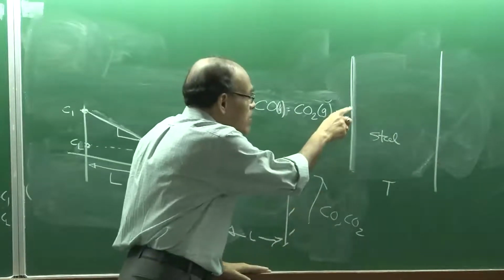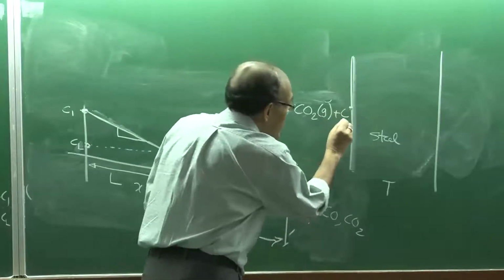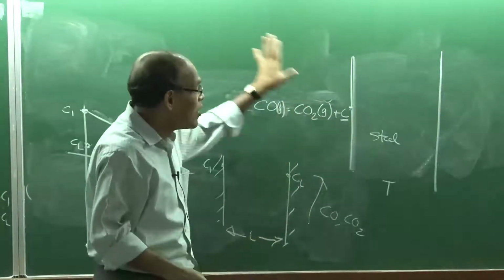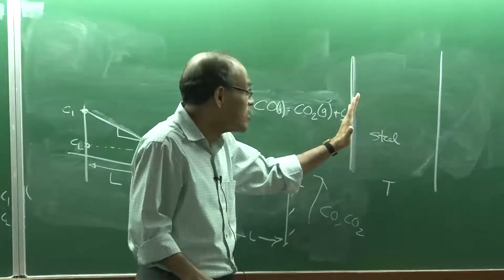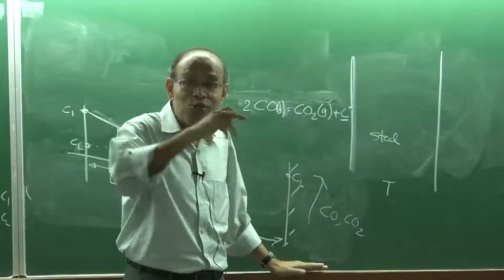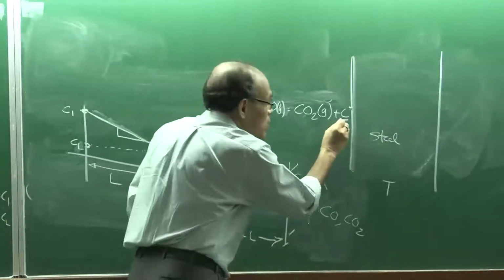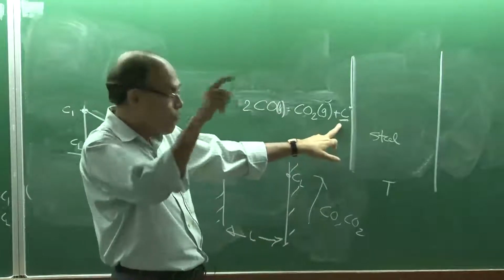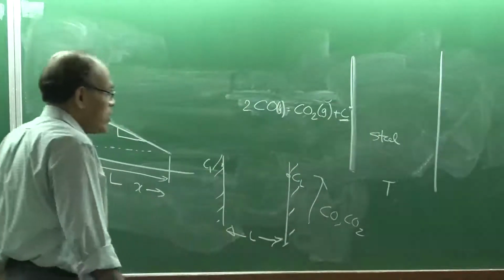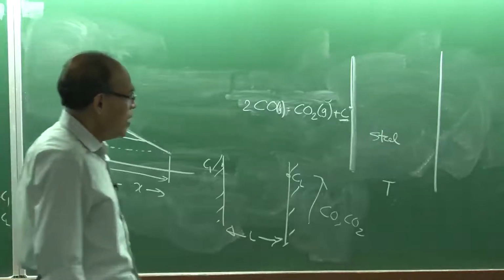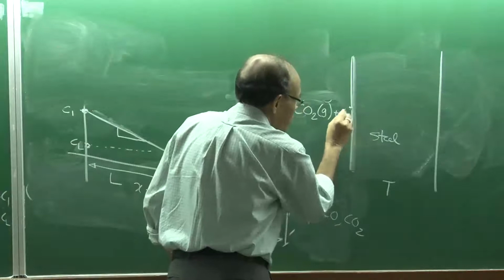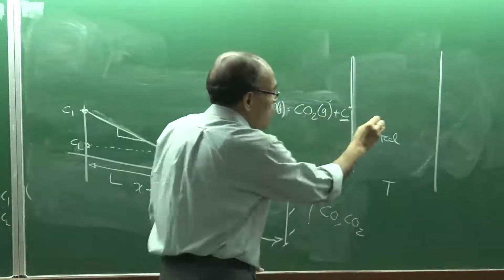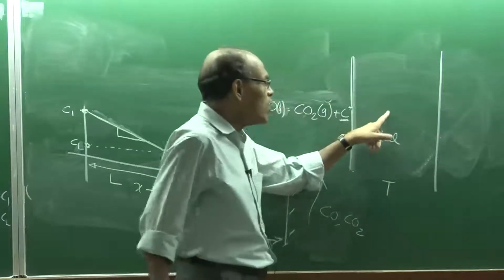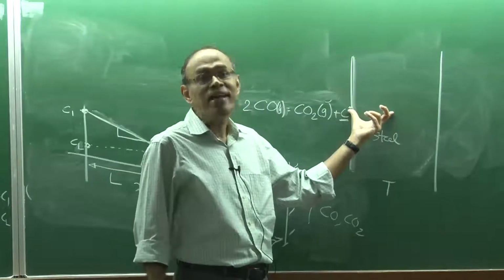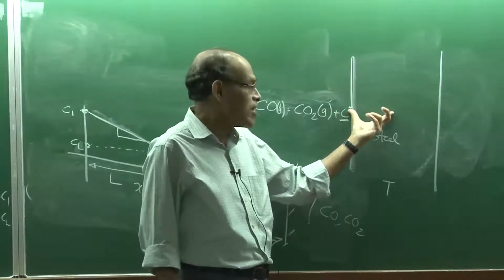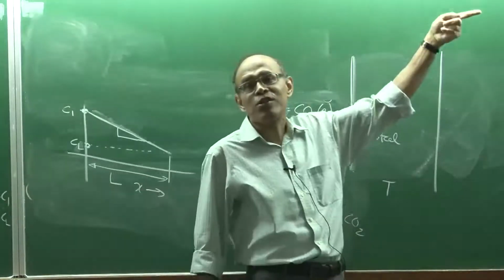The moment this reaction takes place, where does the carbon stay? The carbon is now at the surface. It is not in the gas phase, but this carbon gets dissolved in the solid. It is the surface concentration, in the steel phase, and that is why this notation implies that it is in the matrix of steel. Once it comes, carbon is in the dissolved state here, and if the bulk concentration is much smaller than the surface concentration, then I have created a concentration gradient over this particular distance, as a result of which carbon from a region of higher concentration will try to diffuse inside.